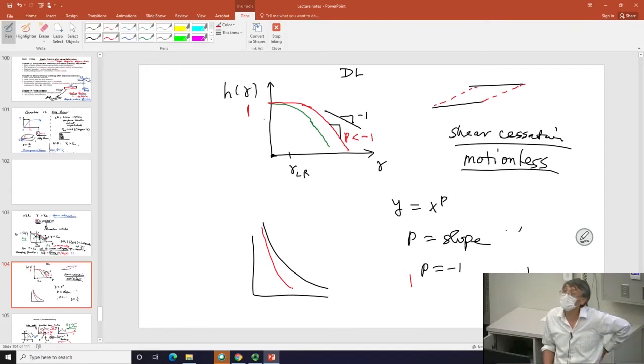So this much is known. In other words, you look at the data from the 70s, you right away know this is the fact: that the slope of your data is smaller, the H function, the damping function, is dropping faster than 1 over gamma at higher gammas.